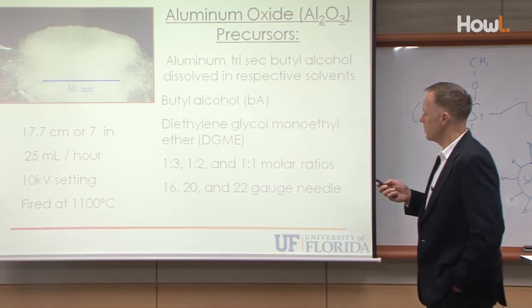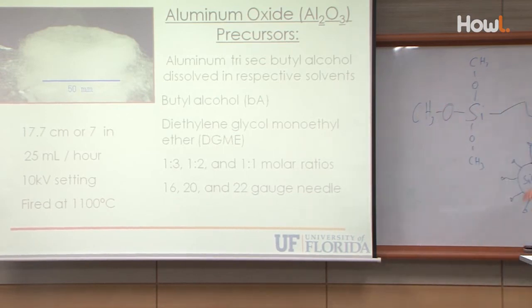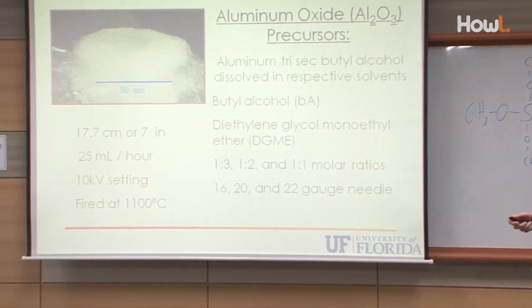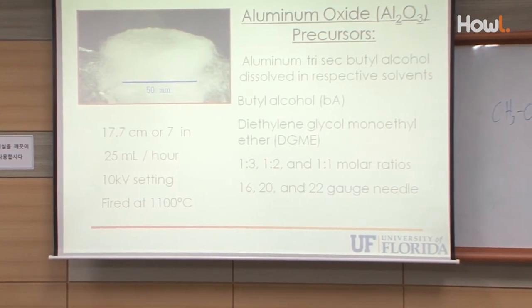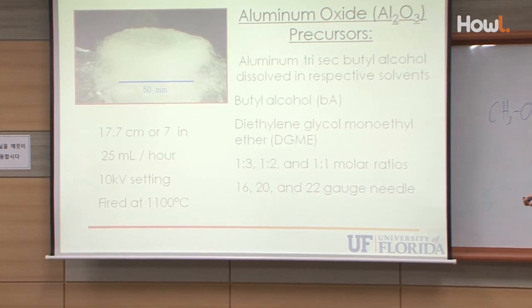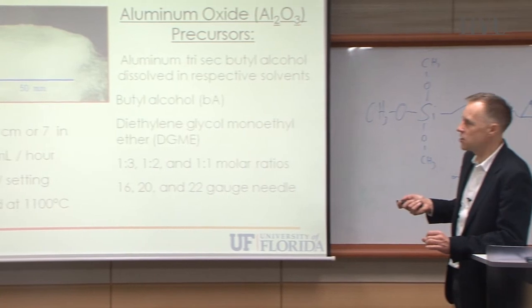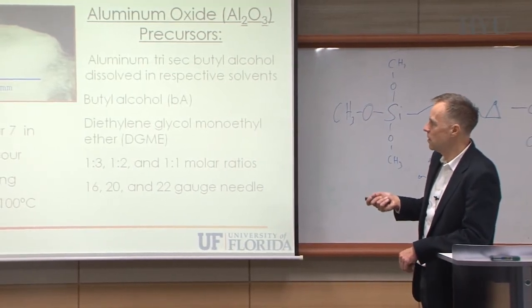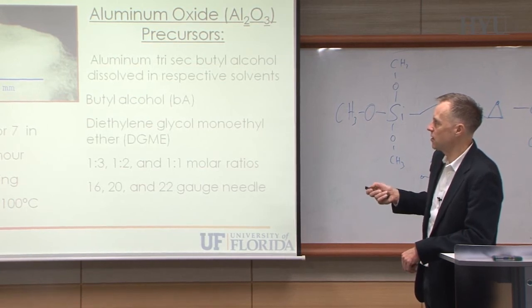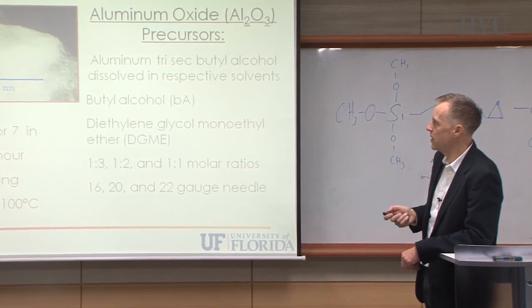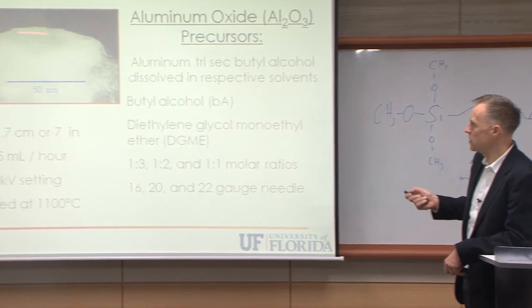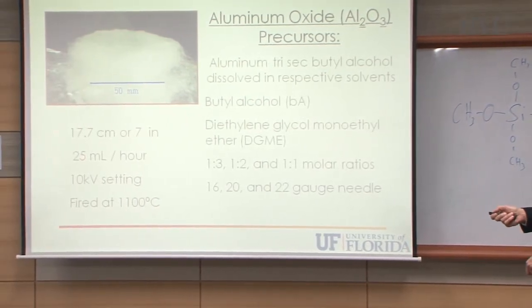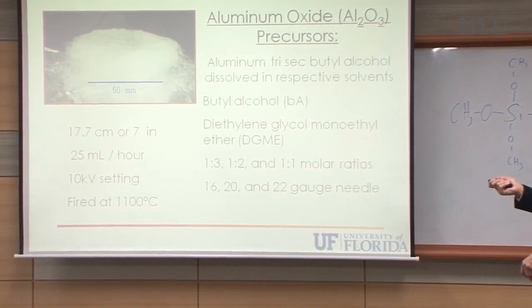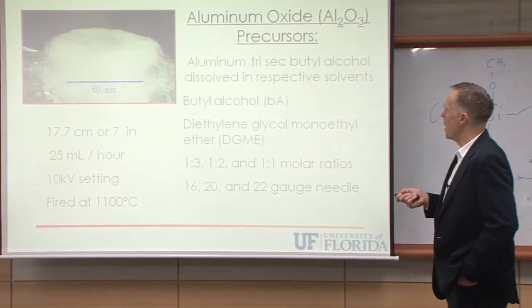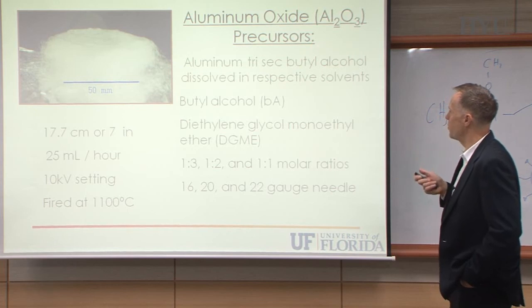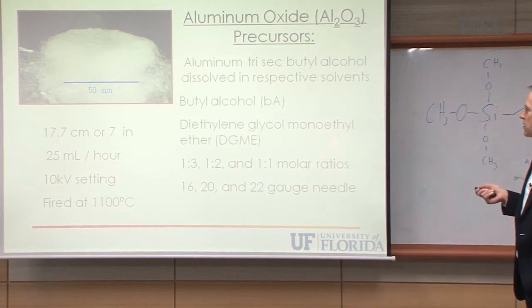And another thing is, of course, you're not limited to just the shapes of a dense fiber. You can make also fibers that are highly porous. And because they're highly porous, the total diameter is larger, so you can make much larger volumes. This is shown here. Within a few minutes, you can coat an entire system, a hot plate underneath that we're electrospinning on, within a short time frame. You see the flow rate is 25 milliliters per hour, so we're not limited to just the really slow flow rates. And here are the precursors for that. It's an alcohol, so it evaporates quickly, and another solvent that doesn't evaporate so quickly.